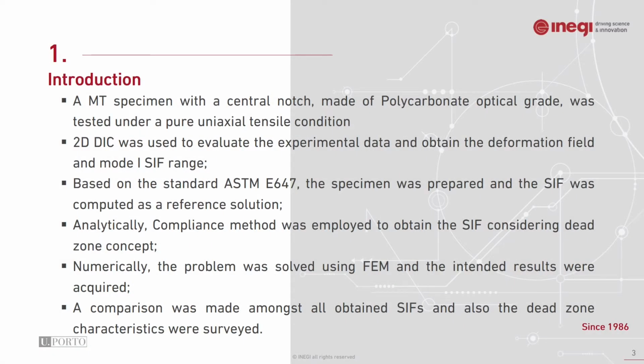Okay, so the first section is devoted to the introduction. Basically, the work that we have already conducted is related to the new analytical solution for the SIF calculation. So in order to prove the concept, it was needed to make some experimental and numerical tests. So in order to do that, a middle tension specimen with a central notch, which is made of optical grade polycarbonate, was submitted to a pure tensile condition in uniaxial loading, and 2D digital image correlation was used in order to evaluate the experimental data and monitor the deformation field in order to calculate the stress intensity factor.